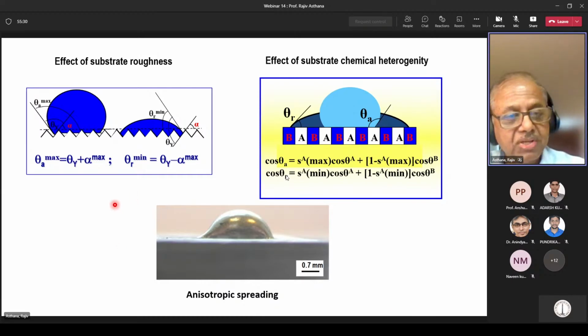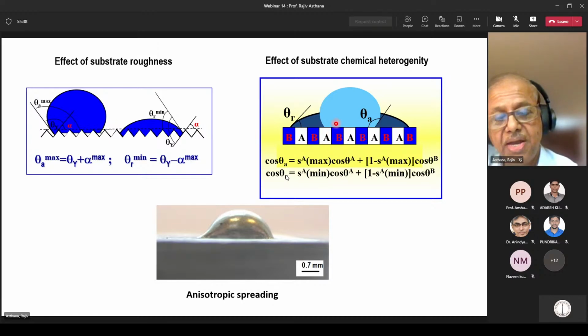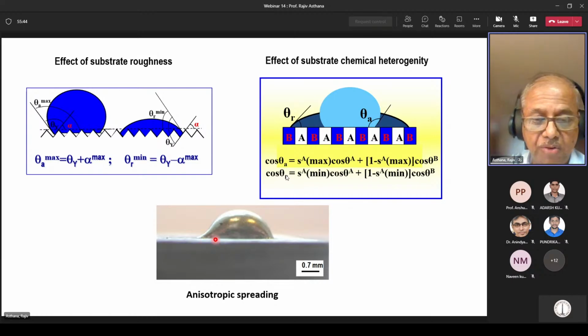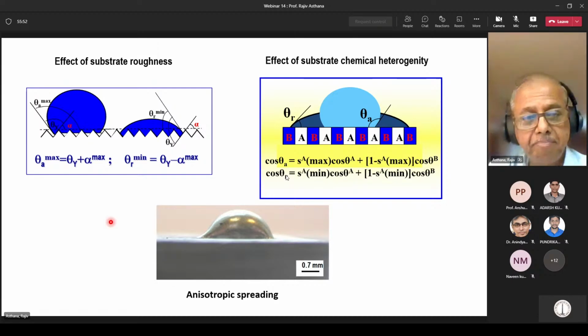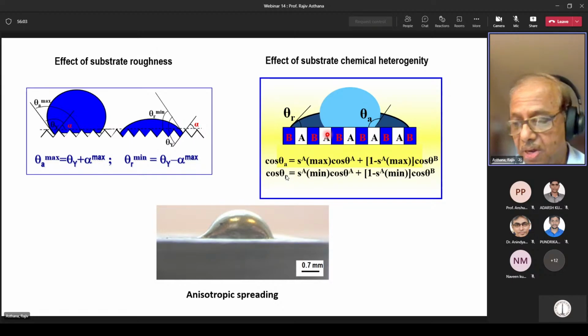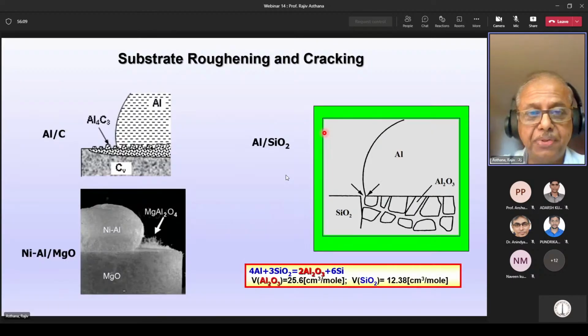And roughness of the substrate, the chemical inhomogeneity of the surface, all these things will influence how the liquid spreads and interacts with the solid. Sometimes the spreading process is not uniform or homogeneous. You have anisotropic spreading, so this side of the droplet spreads differently than the other side. Even in a simple system, like ordinary steel, a liquid will spread differently on, let's say, cementite and ferrite areas or other types of inhomogeneities. So it's quite challenging when you have high temperature systems.